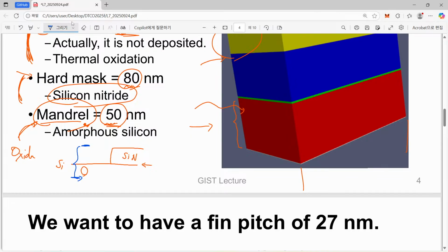So simply speaking, that will be the shape of the silicon dioxide layer. It consumes our silicon. The original silicon layer is converted into silicon dioxide together with oxygen sent from the top, so their interface moves toward the deep substrate.